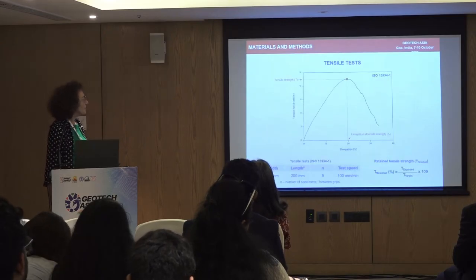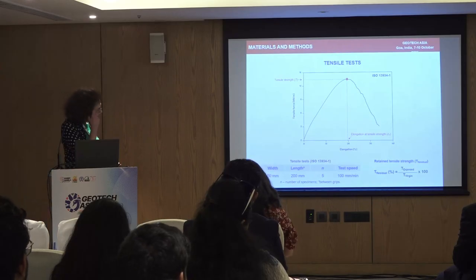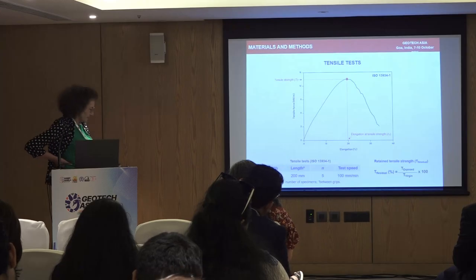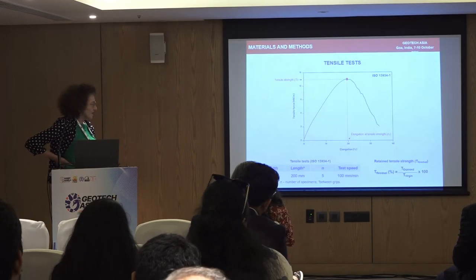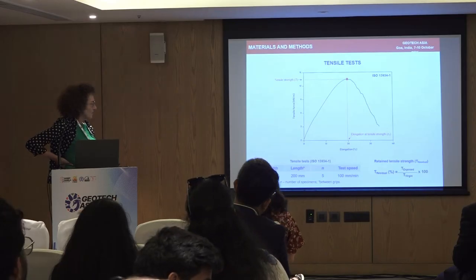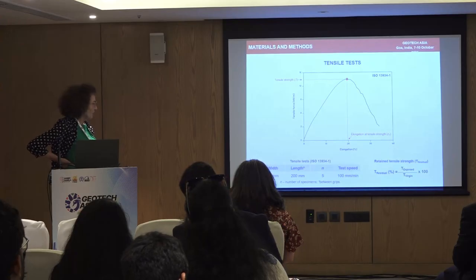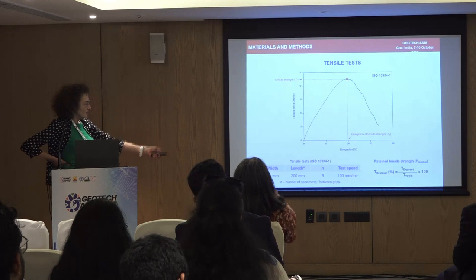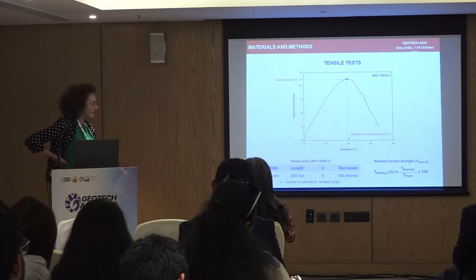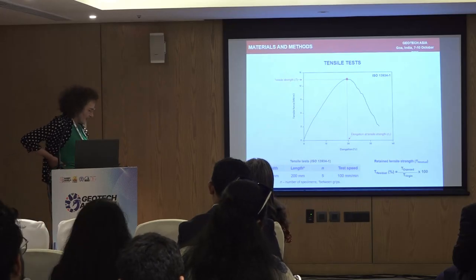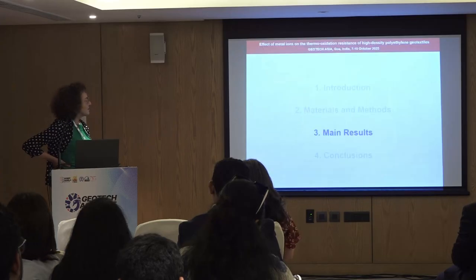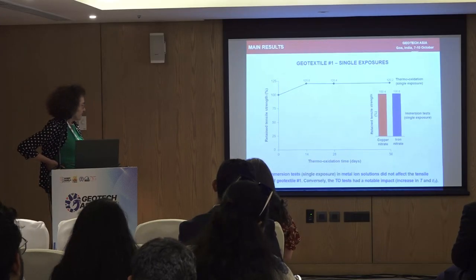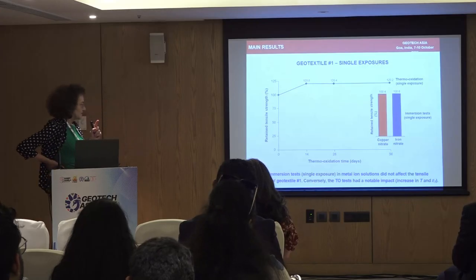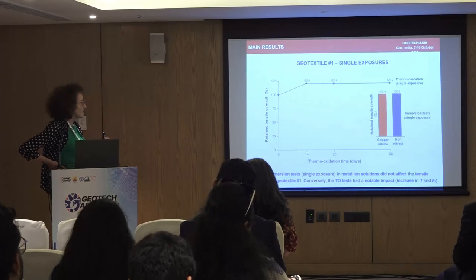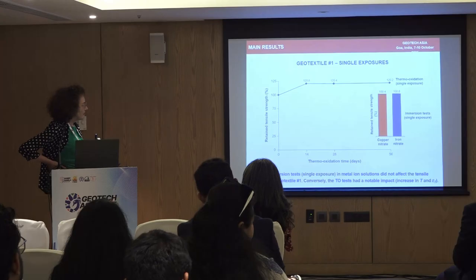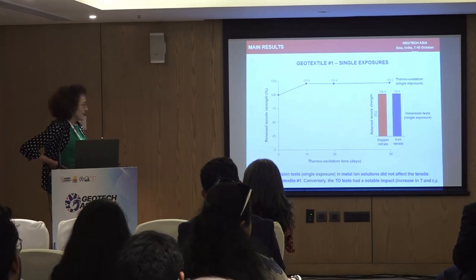Here we have the results of the tensile test, the curves of the tensile test. We use the ISO 13934, and the residual strength is the relation between the tensile strength of the exposed specimen and the virgin specimen. The main results: we can see here that the single exposure in metal ion solutions didn't affect the tensile behavior of geotextile 1.